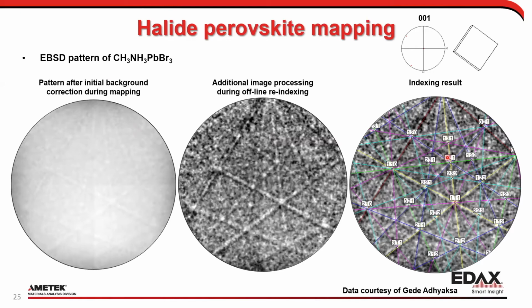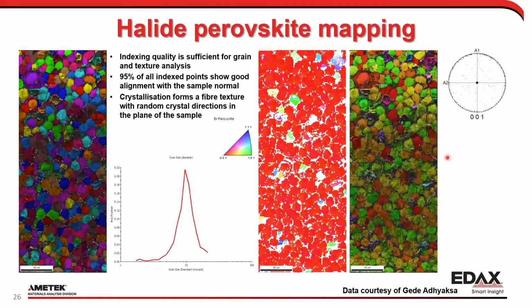So this right here is the halide perovskite material, incredibly beam sensitive. Most of the time, if you look at this crosswise with a beam, you damage the sample. So here again, I can actually look at grain structure and orientation structure, and see that there is in fact a fiber structure to this material. Over on the left-hand side, this is a grain map. You can see individual grains, which means I can get grain size, which we can see is on average about 10 microns. Over here, I can see that there is a texture to the material, and it's mostly red, which means I have a 001 texture. And looking in a different direction, of course, I can see it out of plane as well.